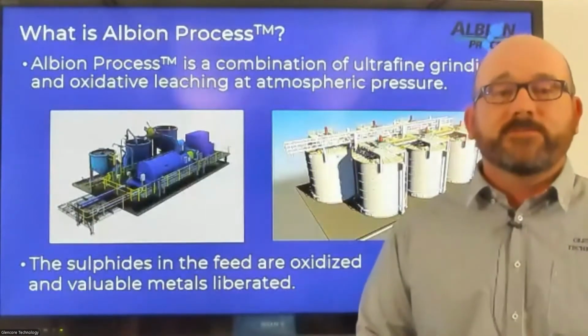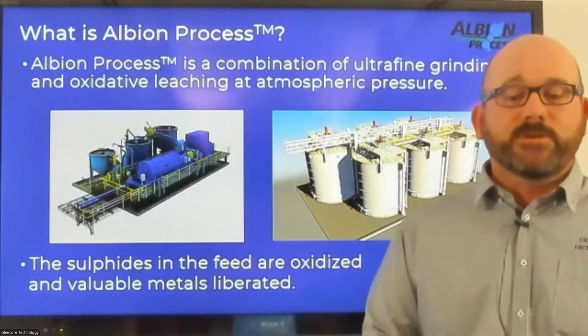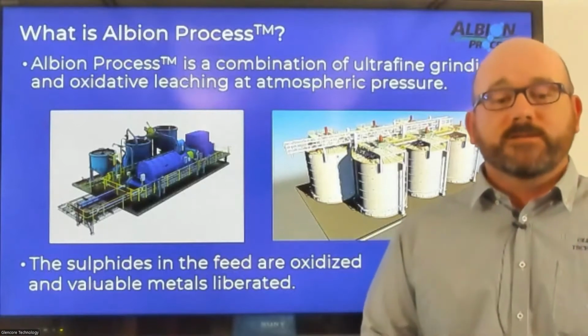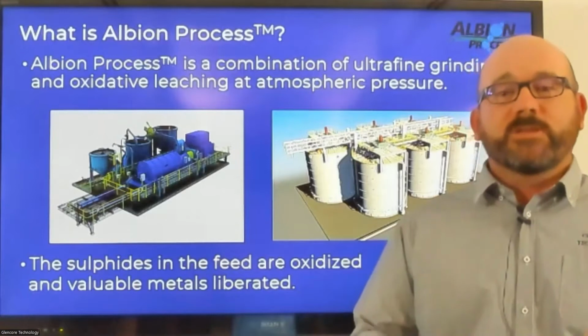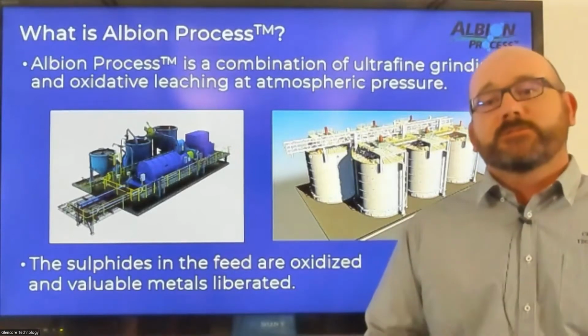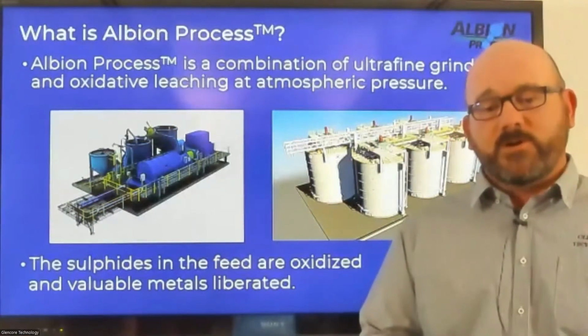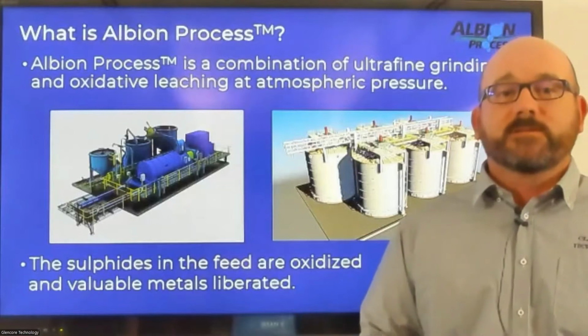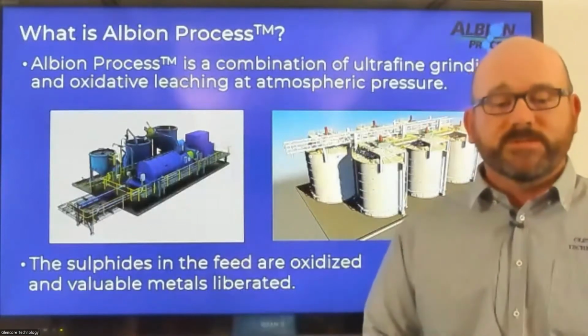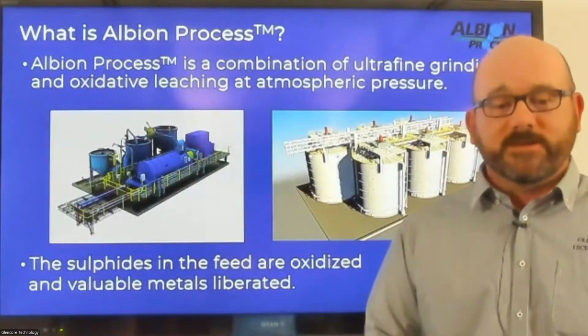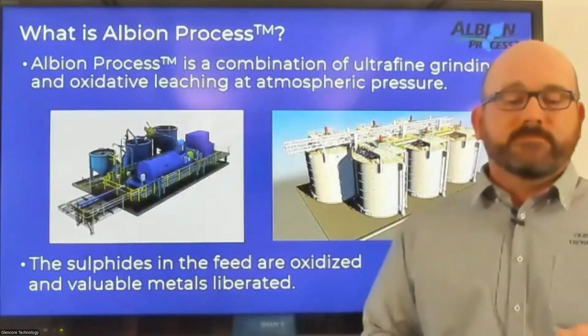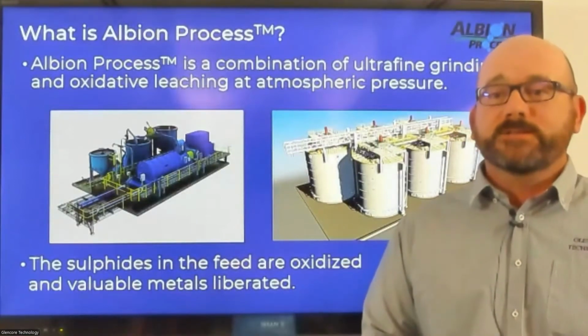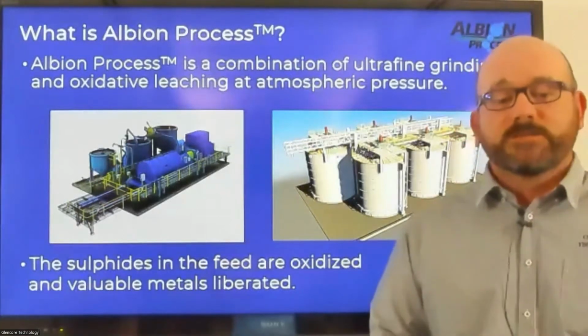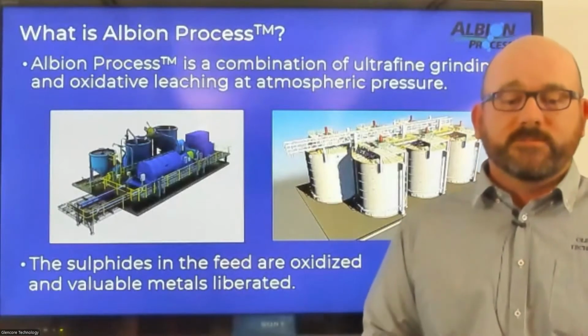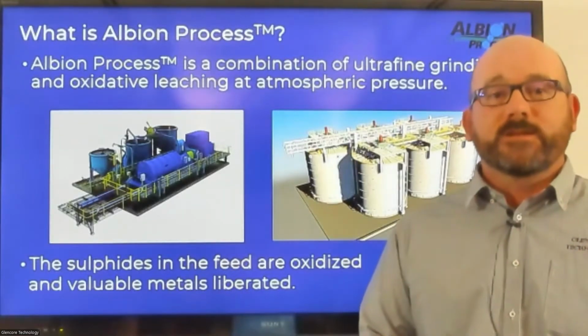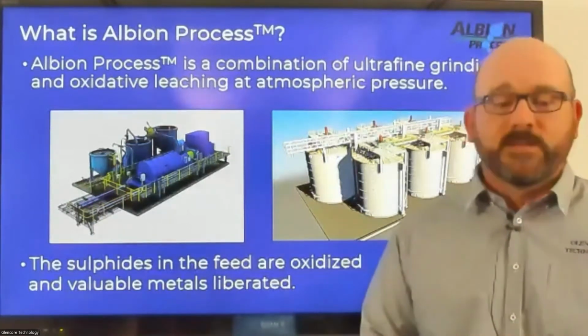In our oxidative leaching phase, Glencore Technology has designed a leach reactor so that we can control the oxidation process very efficiently. We design the whole reactor and supply the whole package, so that we can give you the combination of the two pieces of kit, really to give you the plant that you need. In refractory gold, we're generally looking at pyrite and arsenopyrite concentrates, so really unlocking the gold inside those pyrites so that we can then recover it in downstream processes such as CIL.